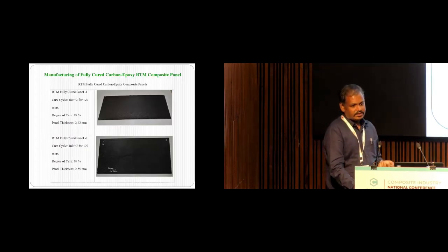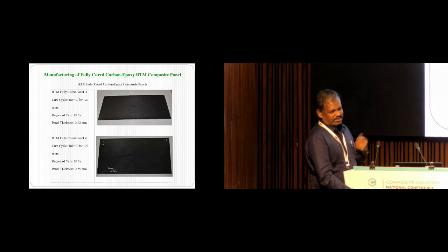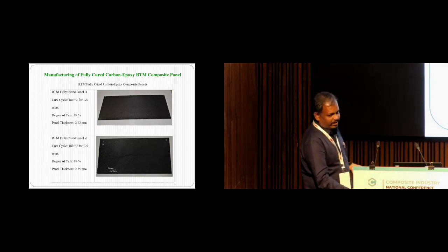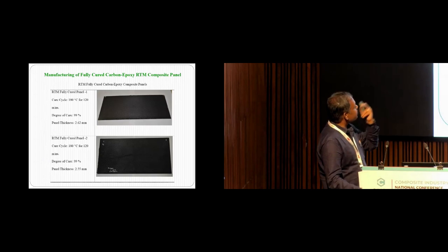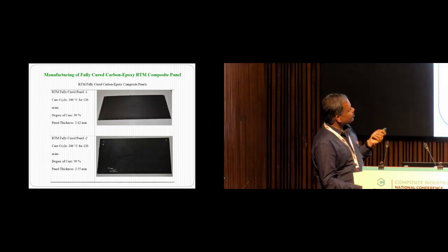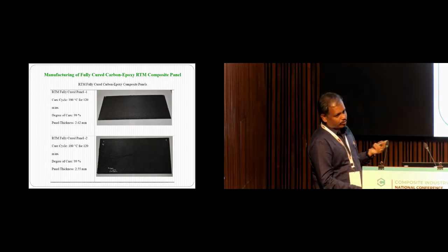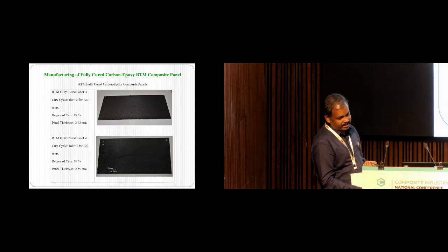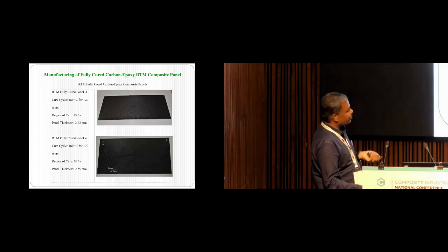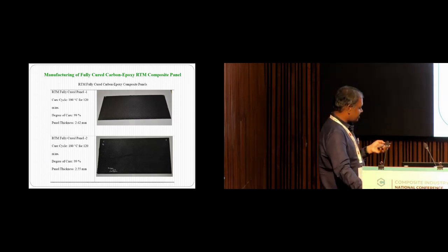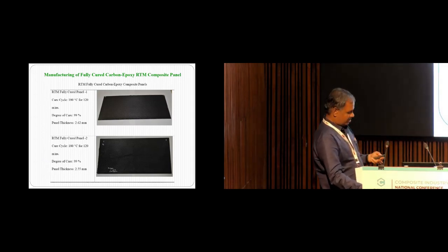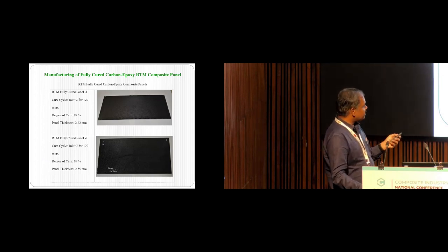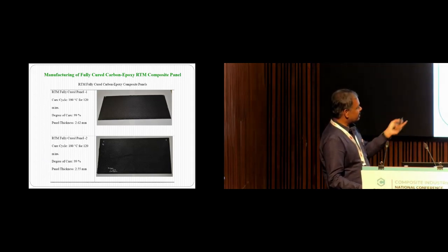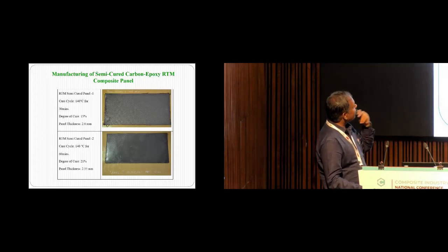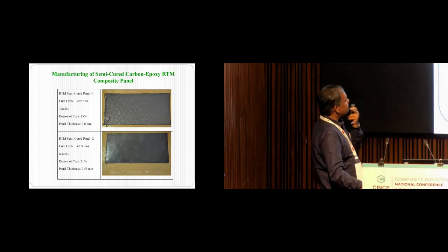We tried out the RTM process, and first of all, as per the resin supplier's cure cycle, 180 degrees for 120 minutes. So for 2 hours, we kept it at 180 degrees centigrade. We got a degree of cure of almost 99%, and we did it one more time to get repeatability. It has 8 layers. Again, we went for semi-cured composite laminate production.